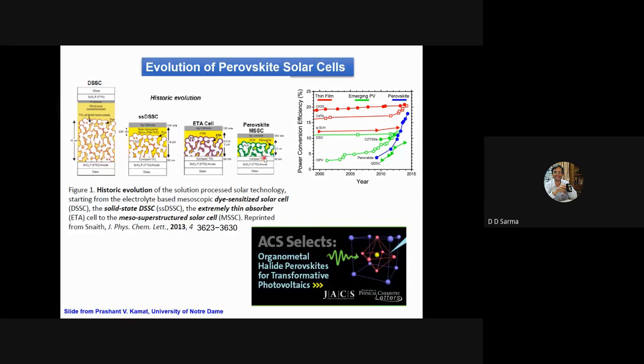And this new material that I'm talking about, this is between 0.5 and 2 micron, and this is now less than 0.5 micron thick. So you can see how thin a material I can do, because it's a fantastic absorber of solar light.